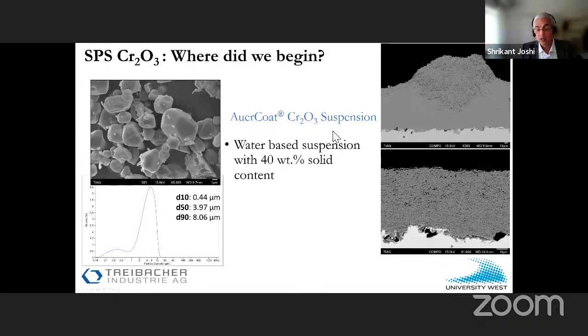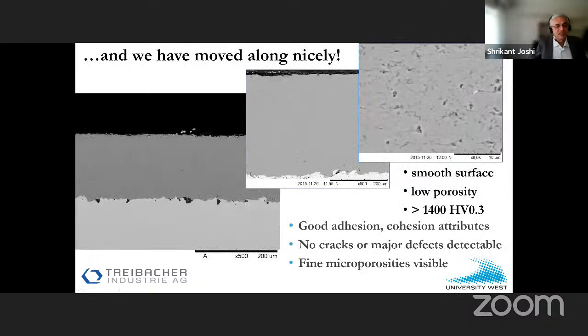More about that later, but when we started, right, this is where we began with chrome oxide, and you can imagine why that happens, right? I mean, this is almost a column head, right? There's a tendency, if you don't do it correct, to form columns when you don't want them and not get columns when you want them, right? So this is where we started, but as I mentioned, gradually we had gotten a pretty good handle of how to avoid those columns, and we've chugged along rather nicely.